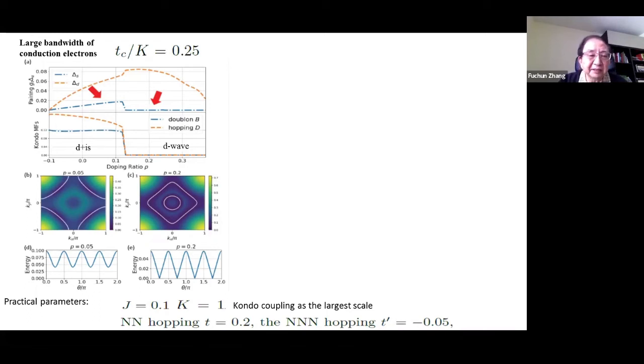Actually, realistically, probably this number will also be reduced. Okay, and these are just the Fermi surface, with doping like 0.05, doping 0.2, okay, the Fermi surface changes. I have 2 Fermi surfaces. So in the parameters, we use the nearest neighbor t equal to 0.2, and next nearest neighbor hopping t prime equal to minus 0.05. Okay.